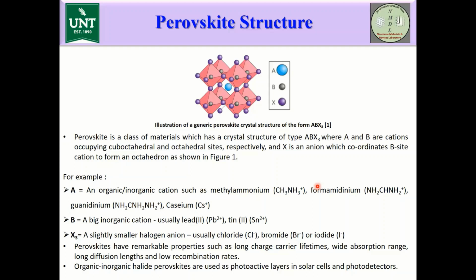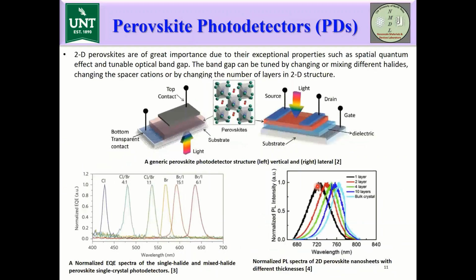Now, these perovskite materials have remarkable properties such as long charge carrier lifetime, wide absorption range, long diffusion lengths, and low recombination rates, etc. That is one of the reasons these materials are great candidates to be used as the photoabsorber layer in photodetectors and solar cells. Now, in our work, we focused on two-dimensional perovskite materials because 2D materials have a few exceptional properties such as spatial quantum confinement effect and tunable optical band gap.